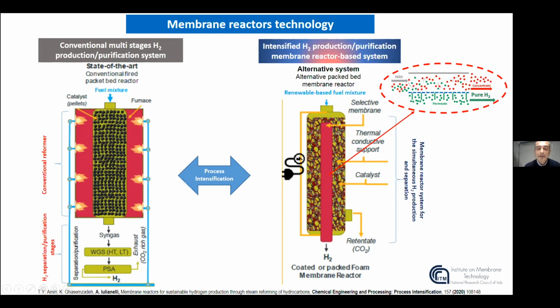In particular, the membrane housed inside the membrane reactor module allows to remove the hydrogen produced during the steam reforming of biomass derivatives such as biogas, bioethanol, biomethanol, and the hydrogen removed from the reaction site by permeation through the membrane is recovered in the permeate side of the membrane reactor module. This allows the so-called shift effect on the reaction systems, because by removing hydrogen from the reaction site, the reaction is shifted towards the products. And this allows to shift also the conventional threshold and to recover as much as possible high-grade hydrogen.